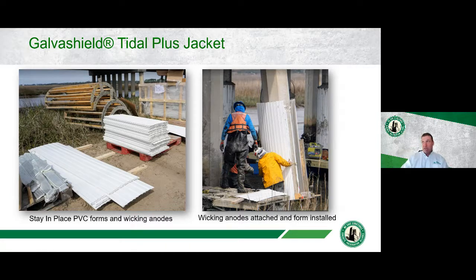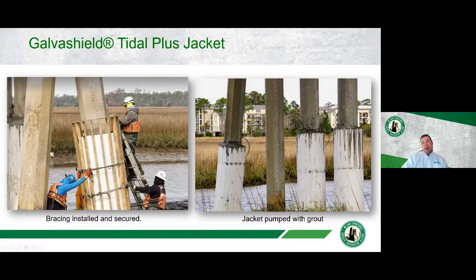You can also see in this jacket that the wicking anodes have been attached to the pile. Again, there are all your cathode and anode connections that need to be made. There's a junction box up here on the opposite side of this pile where all of the connections are being made. Then you're going to use some sort of strongbacks or forming. You want to make sure that the jacket stays centered and isn't deformed during the pumping process, and then it is filled with grout. If you look over here, these jackets were just filled with grout. You can see the wires hanging out on the opposite sides, where they have been routed up through the junction box. Now they're going to come back, put a chamfer on the top, and finish energizing these CP jackets.